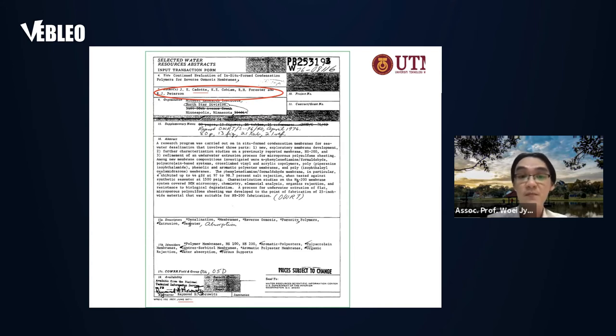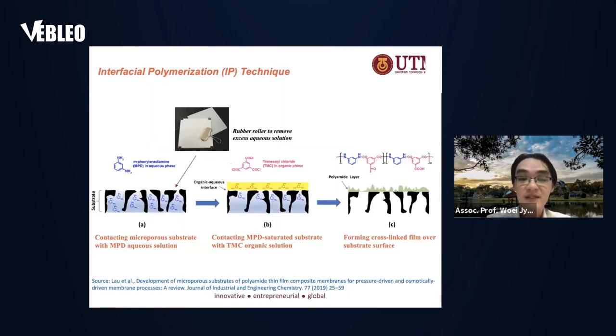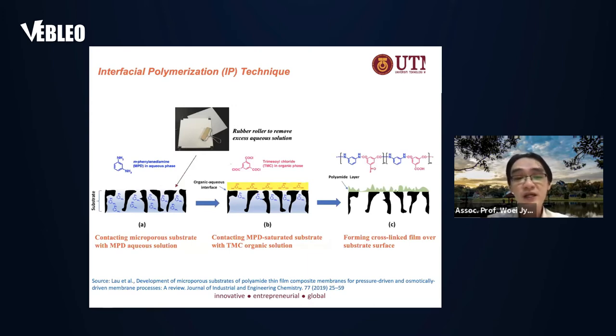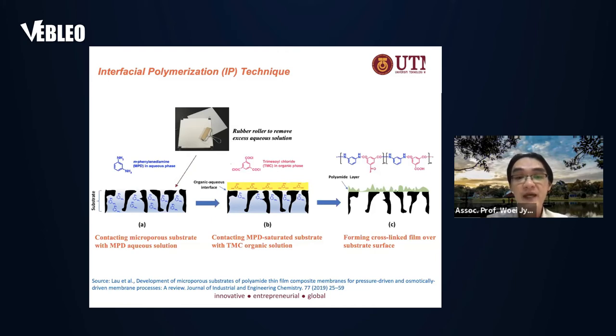This is considered a breakthrough compared to the first asymmetric membrane invented by Loeb-Sourirajan in the 1950s. As I mentioned, when you want to fabricate the polyamide layer on the surface, you need two monomers. After you pour the first monomer on the substrate, you need to use a rubber roller to remove the excess aqueous solution. This ensures that the polyamide layer you make has good properties without any air bubbles trapped within the polyamide layers.